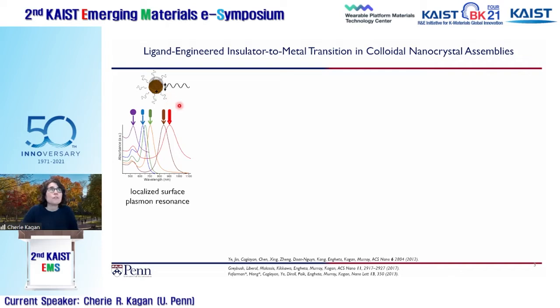They're really well known for their localized surface plasmon resonance, the idea that when you shine light, the free electrons in the metals will oscillate back and forth with the electromagnetic field. That creates a dipole that we see either in absorbance or, for larger particles, in scattering, known as the localized surface plasmon resonance. And as Ray showed in the chemistry, you can tailor size and shape. He showed a lot about spheres up to nanorods, which is often used as a way to tune that resonance in metal nanoparticles.